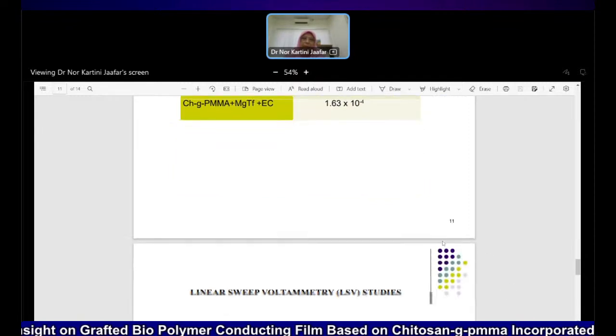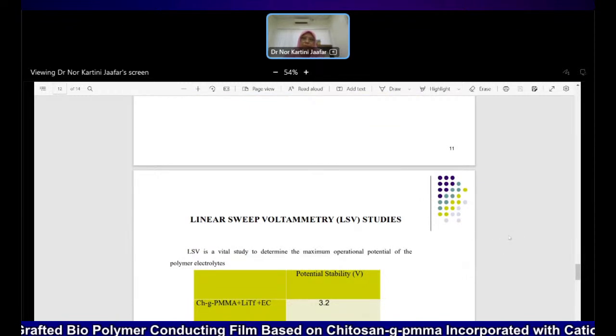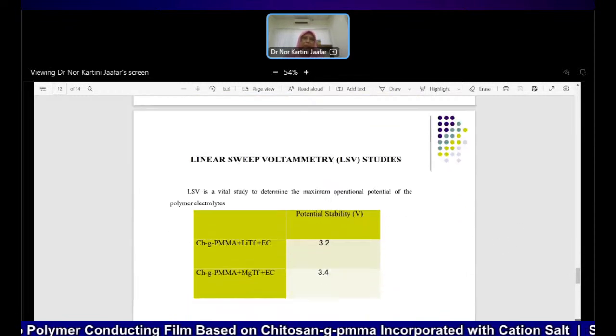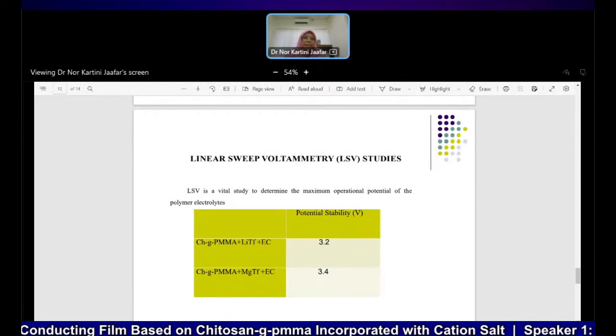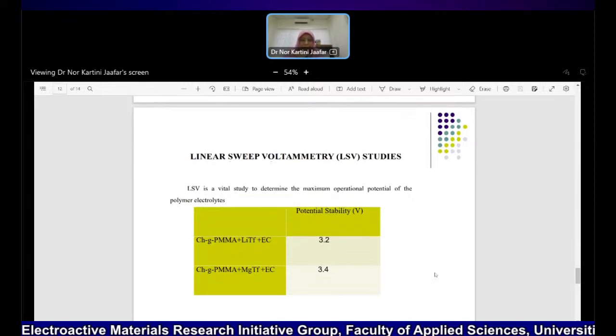And then when we study the window stability, what is LSV actually? LSV study is to determine the maximum operational potential of the polymer electrolyte. So we can see that the potential stability voltage for both the lithium system and magnesium system is above 3.2 and 3.4 volt. This is good enough potential stability when we fabricate any electrochemical device.